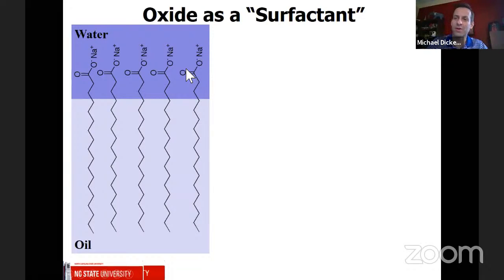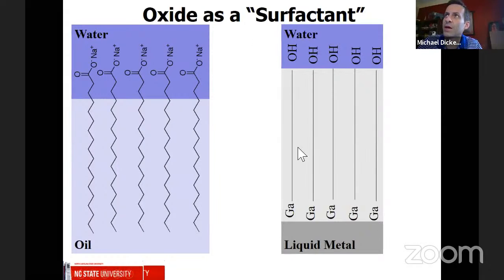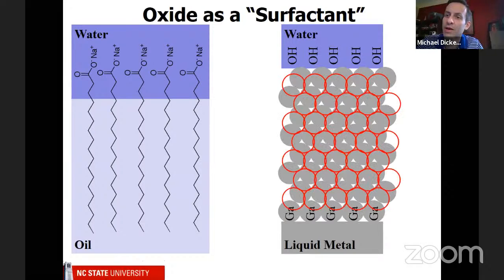And so it's sort of like holding hands between two enemies. It spans this interface and lowers the interfacial tension. If you were going to design a surfactant for liquid metal, you would want to have gallium at this interface with the liquid metal and OH groups at this interface with the water. If you look at this diagram, you realize right away that I'm not a chemist, and a chemist would never draw it this way. But what I'm trying to depict actually is the oxide layer.